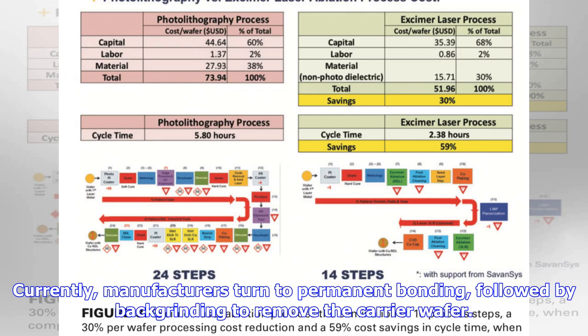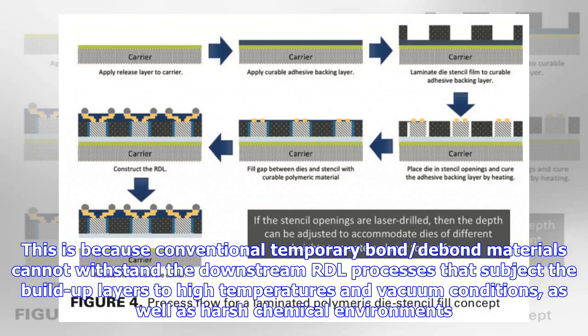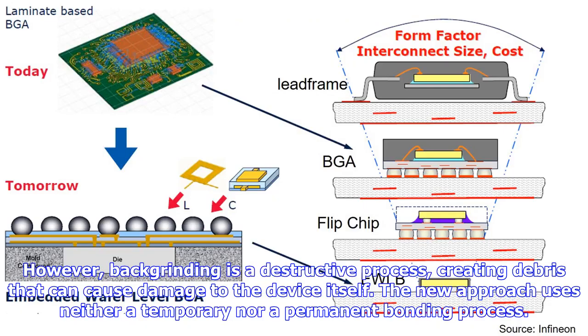Currently, manufacturers turn to permanent bonding, followed by back grinding to remove the carrier wafer. This is because conventional temporary debond materials cannot withstand the downstream RDL processes that subject the buildup layers to high temperatures and vacuum conditions, as well as harsh chemical environments. However, back grinding is a destructive process, creating debris that can cause damage to the device itself.